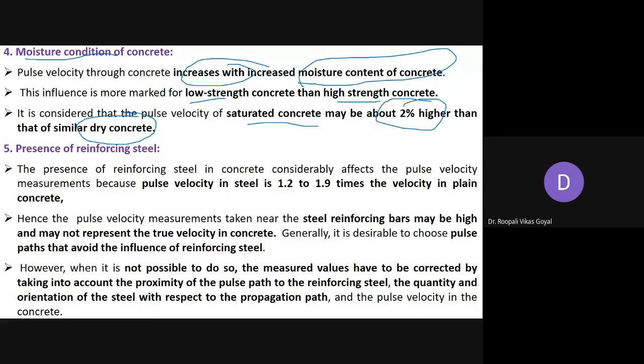Also there is a pronounced effect of reinforcing steel. If steel reinforcement is there, its pulse propagation will be different as compared to concrete. So pulse velocity measurements are also affected by the presence of reinforcing steel bars, because the pulse velocity in steel is 1.2 to 1.9 times the velocity in plain concrete. So whenever such reinforcing bars are there, it will give you a higher result, and it will not give the true velocity of the concrete.